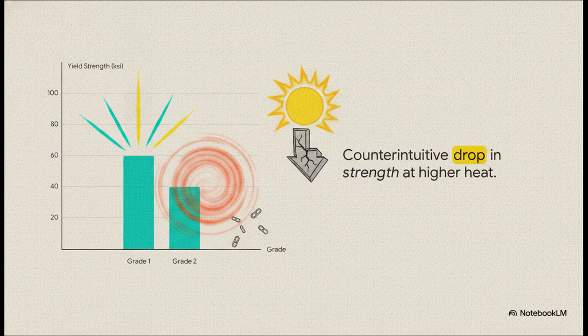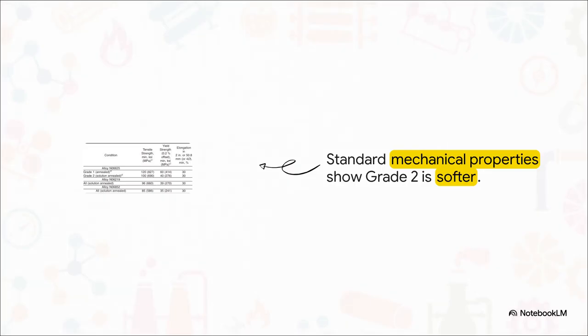You'd probably assume that treating a metal at a higher temperature makes it stronger across the board, right? But if we look at the minimum yield strength, grade 1 requires 60 ksi, while grade 2, our high-temperature hero, actually drops down to 40 ksi. The mechanical properties data verifies this completely.